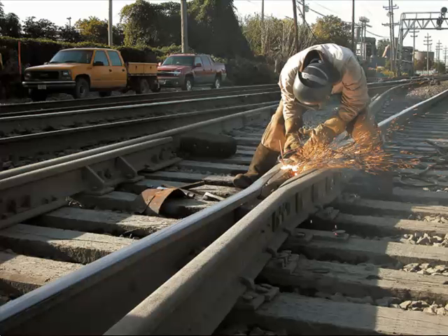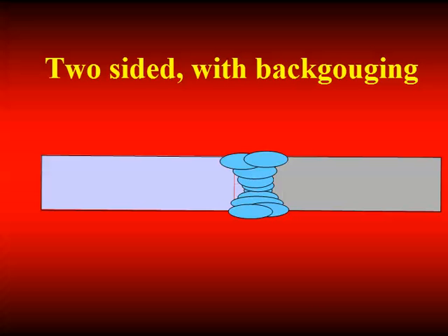With air arc gouging, we use the same kind of welding equipment that we'd use for welding, but we have a different kind of torch. Instead of a metallic electrode, we have a copper-coated carbon electrode. The electrical power flows through that carbon electrode. In the torch are a couple of ports through which compressed air is passed. So you light the torch, you put on the compressed air, the torch liquefies the metal, the compressed air blows it away. And that shower of sparks there is the metal being blown away. So that's the process called air arc gouging. After we gouge the root, whichever method we use, we weld up the joint.